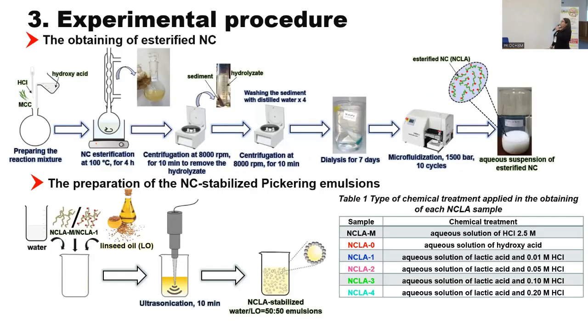In what concerns the experimental procedure, the chemically modified nanocellulose was obtained by the esterification of microcrystalline cellulose with hydroxy acid, which is lactic acid, at 100 degrees for 4 hours, followed by microfluidization for 10 cycles. We can see from table 1 that we have tried many recipes.